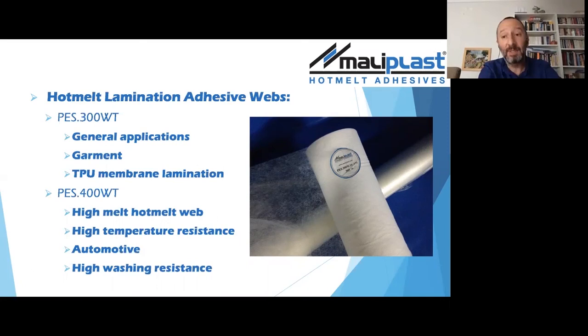It can be garments, even in the automotive applications. For example, for the headliner applications, we are recommending our polyester 300 WT. Then we have got polyester 400 WT. Actually, polyester 300 has got a melting range around 95 to 100 degrees. Polyester 400 has got very high melting range, which is around 140, 145 degrees. This is a big advantage for the high washing resistance. It is resistant even to 80, 85 degrees washing cycles. But at the same time, it is resistant to high temperatures, especially for the automotive sector.